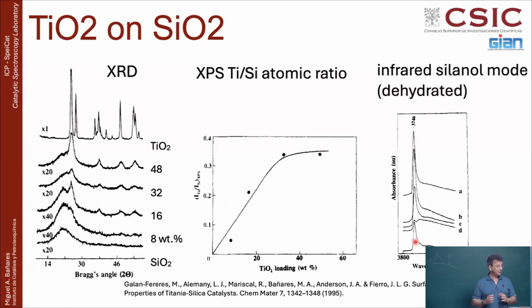But now you're going to make a house on this table. What happens? Will you see the table again? Yeah, because all these bricks will be here, and then again, you have the surface available. Okay, when you go above the monolayer, you no longer have a molecularly dispersed titania all over the silica. You don't have a monolayer of molecularly dispersed titania. Now this titania is gathering again. And when they gather again, the surface of the support is free again. So that is very interesting because you are going until you cover the support and then everything redistributes. You cannot stabilize so many titania species, then they aggregate. And when they aggregate, you are also losing the dispersion and you are getting the support.